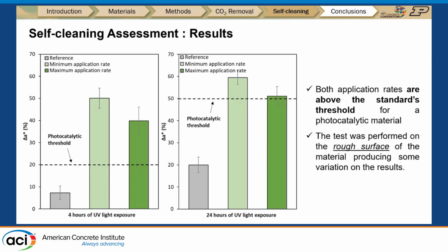So this is our result. We can see that both treated samples, after 4 hours and 24 hours, met the photocatalytic threshold for being considered a photocatalytic material. However, we are doing this on a rough surface, and we are also repeating this on a smoother surface to see how the optical properties change, and if this effect can be more advanced.